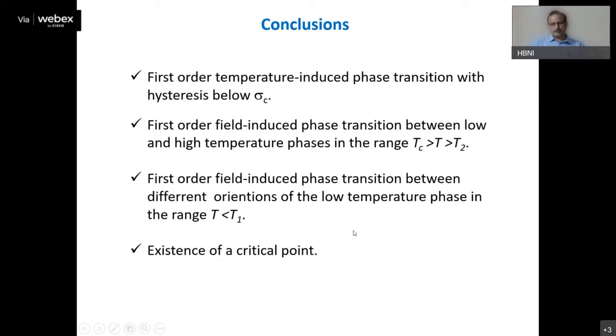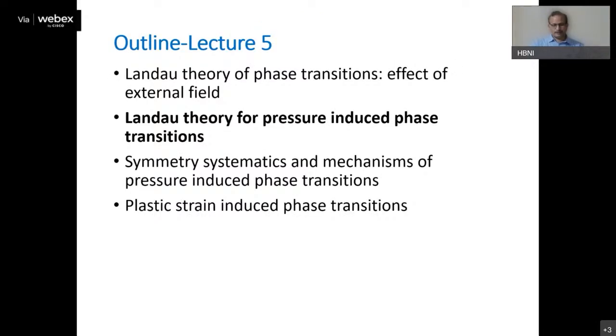So as we discussed, if we describe phase transition in terms of strain, for example, in case of martensitic phase transition, this external field is actually stress. So we can describe pressure-induced phase transitions this way, considering strain as an order parameter. So I will just briefly discuss how Landau theory is extended to describe pressure-induced phase transition.